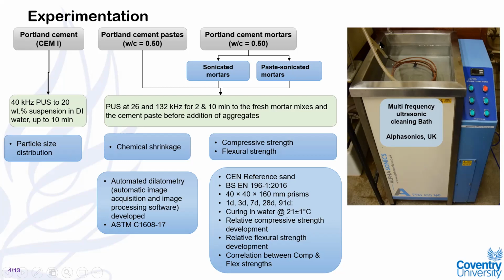We treated cement paste and measured the chemical shrinkage using a developed automatic dilatometry setup. For the cement mortars, we measured compressive strength and flexural strength development through different curing ages up to 91 days on mortar prisms, 40 by 40 by 160 millimeters, using a reference sand based on the requirements of the BS EN standard. Two scenarios were considered in the case of mortars: sonication of mortars at once, and sonication of paste and then adding aggregates to the system.